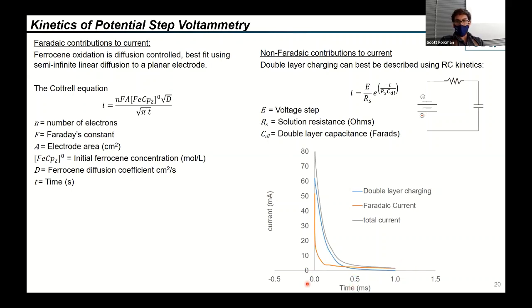We're looking here at about 0.5 milliseconds. And then it goes down to some smaller current value here. Now, if we look at the double layer charge, we see that it's higher than the Faraday current at the beginning, but then it actually decays faster. So the double layer charging decays much faster because it's exponential. The Faraday current doesn't decay quite as fast, and then at longer times, the Faraday current dominates.